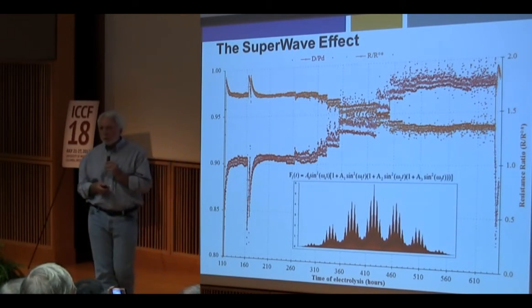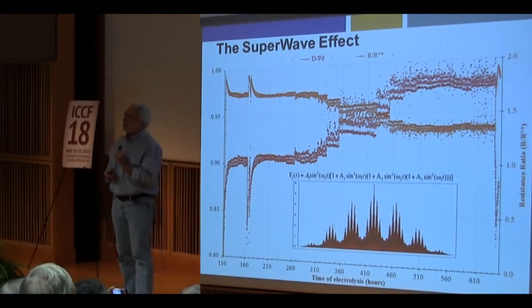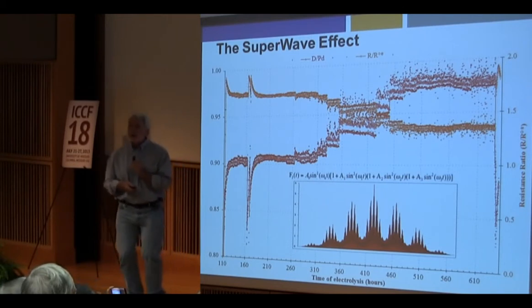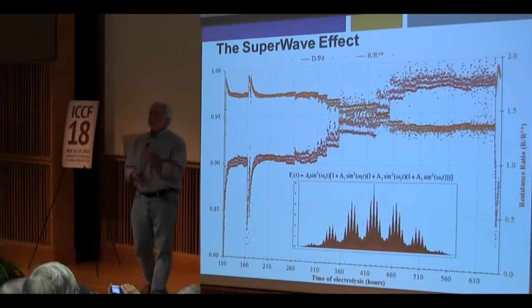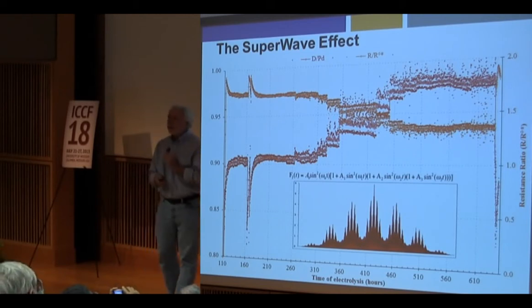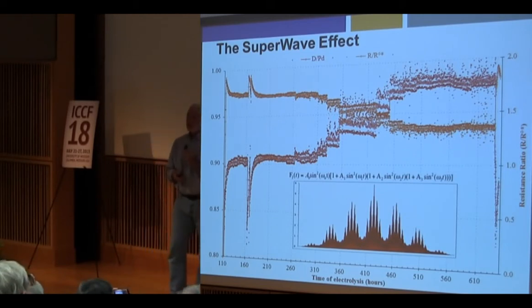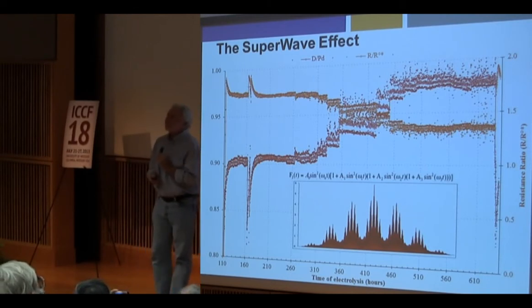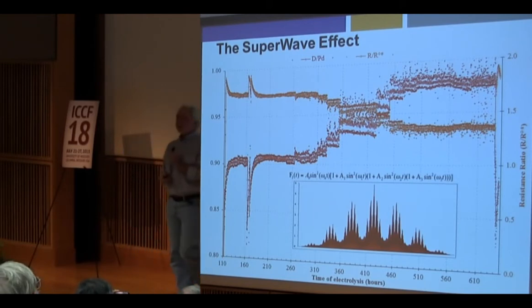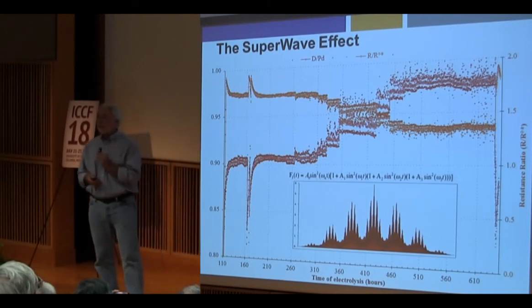And the problem quickly became apparent to us because it's a non-linear response process. What you gained on the upside, you more than lost on the downside. So you could fluctuate the loading of your surface fine, but always with a result of net loss of loading. So you get a high modulation, high flux condition, but you couldn't have a high loading condition. You couldn't have both things simultaneously by any waveform that we thought of ourselves.